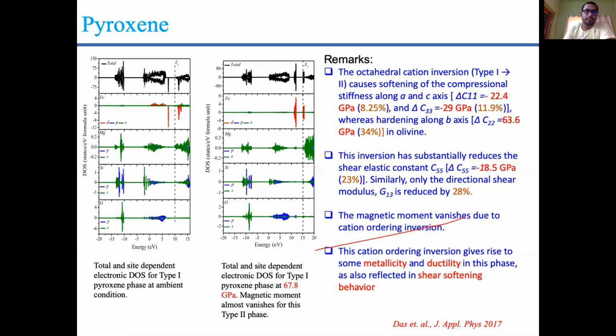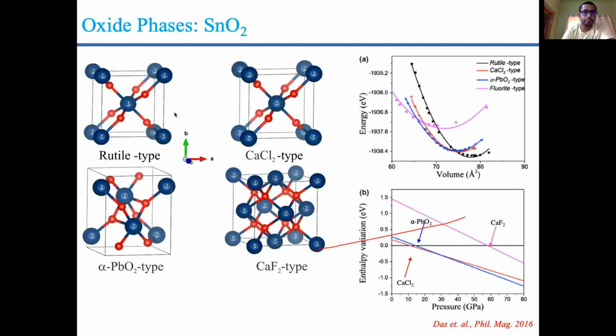This is where I started with my DFT calculations, long back in 2015 or 2013 probably. I studied the sequential phase transition in the SnO2 phases because it has a transition from rutile to CaCl2 to alpha PbO2 to CaF2 phases. In the upper panel, you can see the energy volume curve, and I measured the transition pressure from this curve